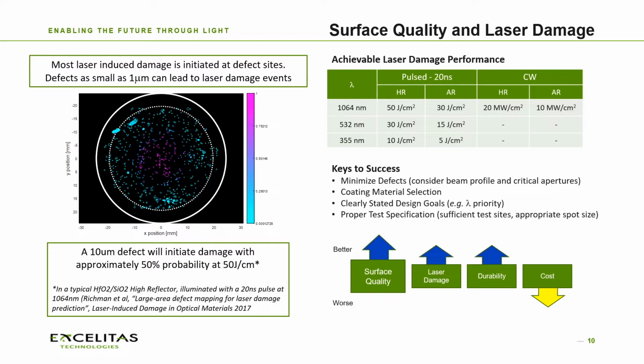As a rule of thumb, based on some previous work that we've done, we find that a 10 micron defect has a damage probability of about 50% at 50 joules per square centimeter for a 20 nanosecond laser pulse. 20 nanoseconds is a common reference point for pulse laser damage. And it's important to understand that all of this is statistical. There's always a probability. We're testing with very, very poor coverage of the surface, and so we're only getting a small glimpse of the actual damage performance of any given surface.